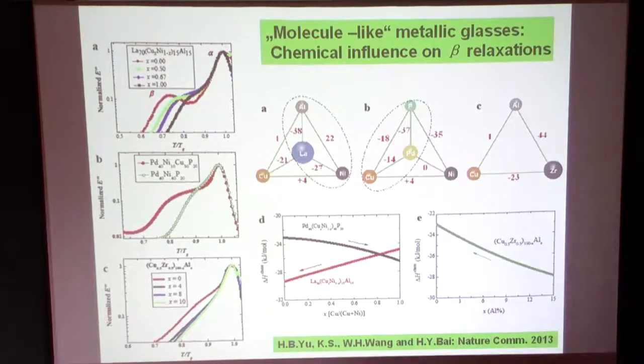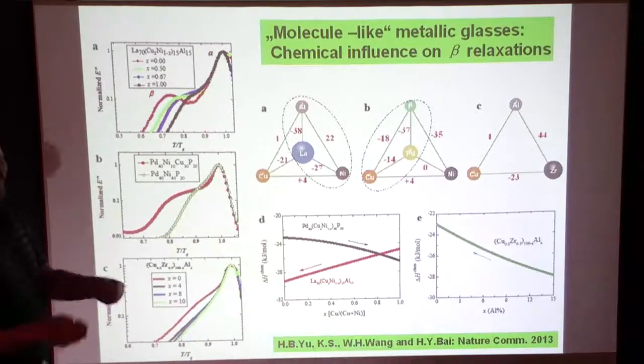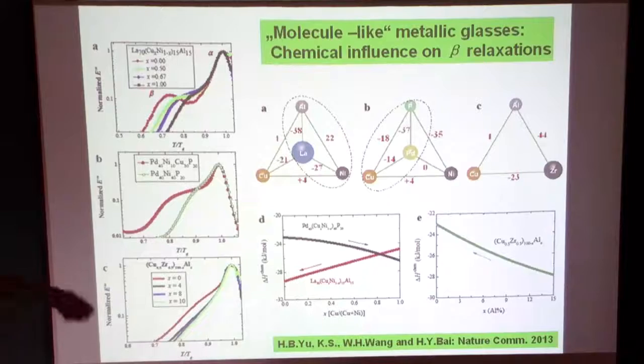Frustration is always there, I told you about the unhappy atoms. The frustration is always there because you want to make a homogeneous, close-packed system actually, right? And there are stresses in between, huge stresses, because you have orientations between the different ones. If you want it as a spin glass system, then you have different orientations between the local motifs, and then they are not space filling. Density fluctuations. The minus sign means repulsion then? No, attraction. But the plus is then repulsion, yeah. Well, this is just the terminology of the material scientists.